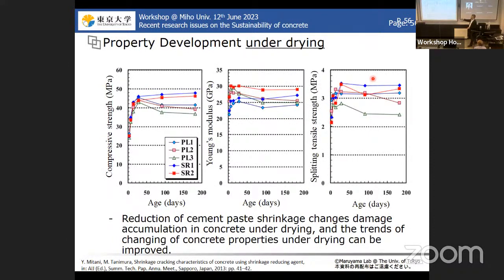So this is the compressive strength development as a function of time. And as you see, when we dry the specimen, exposed at the day of 7 days, we see the reduction of the concrete. But in case of adding the SRA, we see no reduction of the compressive strength. So the damage inside of concrete is mitigated by the reduction of the shrinkage of hardened cement paste. So compressive strength was kept under the drying process.